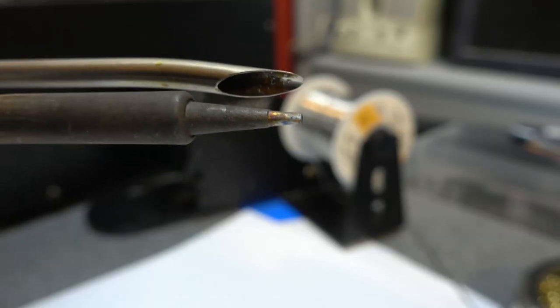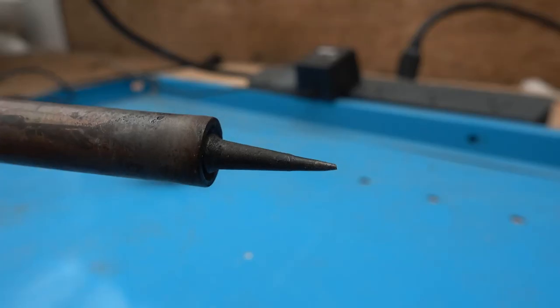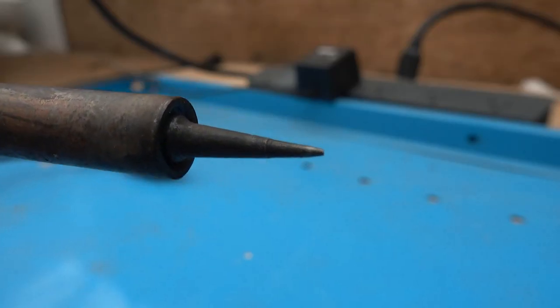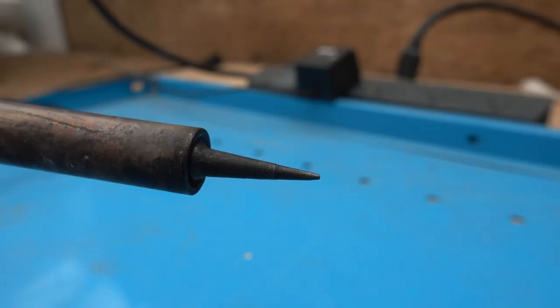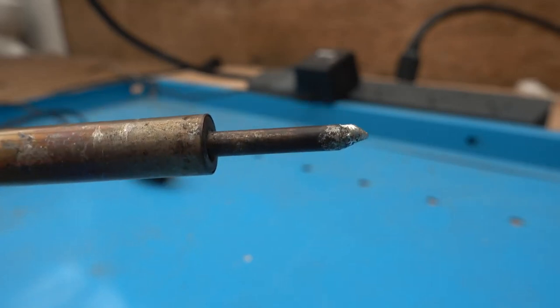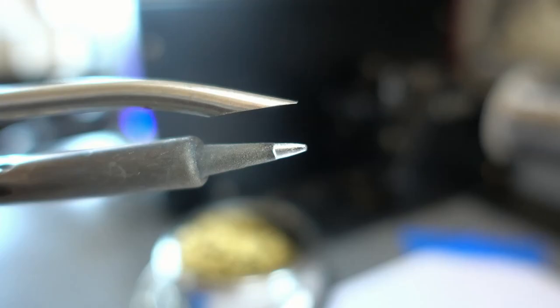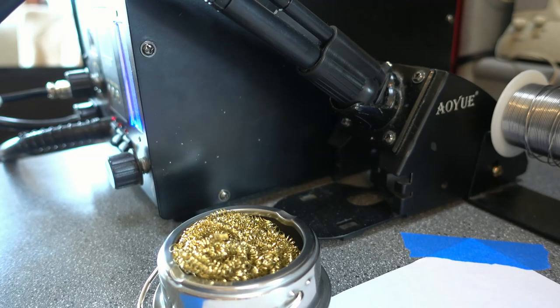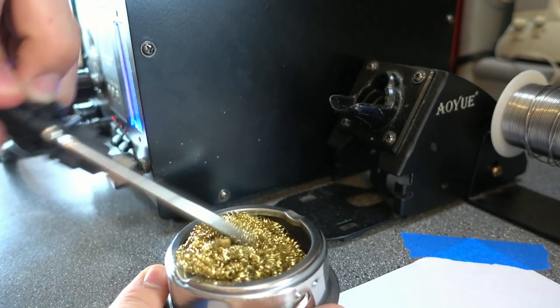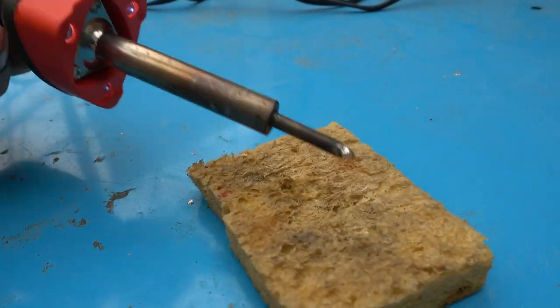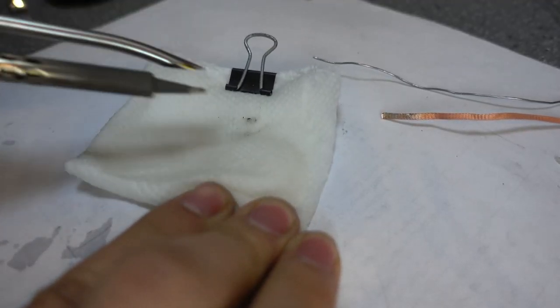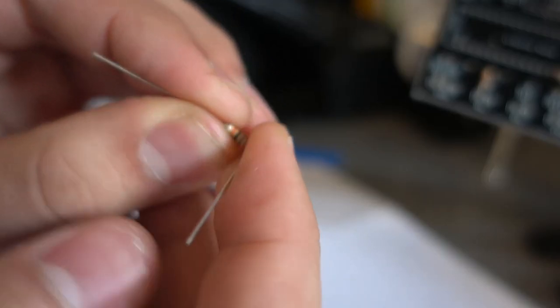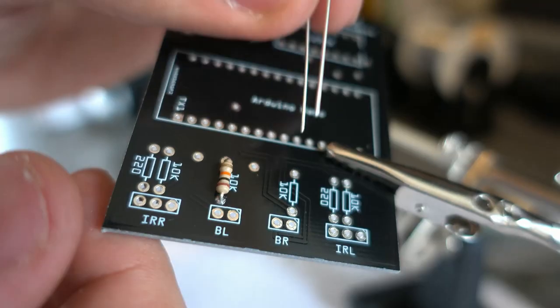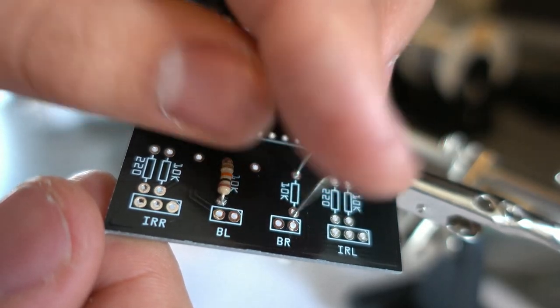The biggest cause of problems when soldering is a dirty tip. Because of the intense heat, oxides form over time and prevent heat from transferring properly, leading to messy and incomplete joints. A dirty tip has a brown or black appearance, while a clean tip is shiny and bright. Luckily, cleaning the tip is easy. My preferred method is brass wool, but you can also use a damp sponge, or even a damp paper towel, in a pinch.